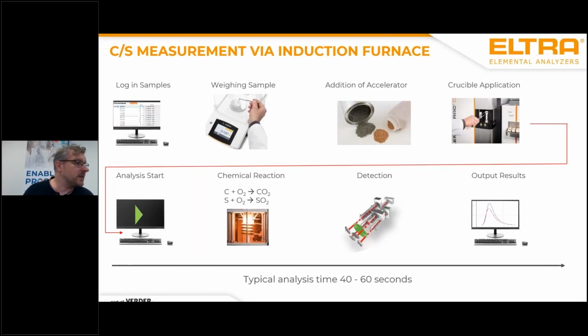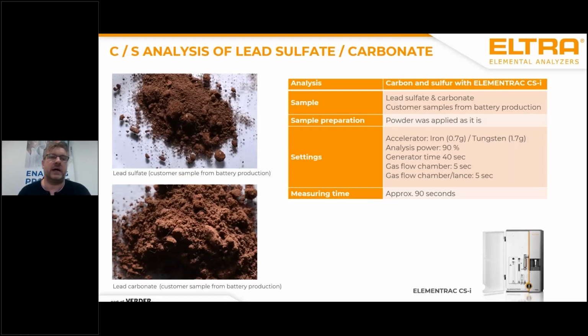And typical results for this kind of analysis, I have results of different samples, and these are customer samples. The one you see on the left side is lead sulfate. This was from a customer sample, and I also have lead carbonate. And these are typical samples for lead-based batteries. When you have, for example, samples which are based on lithium or maybe manganese, this is no problem for the analyzer because it also can be combusted and analyzed for carbon and sulfur.